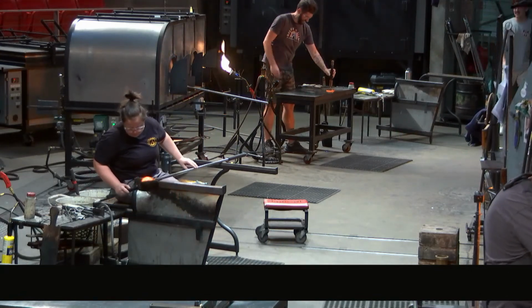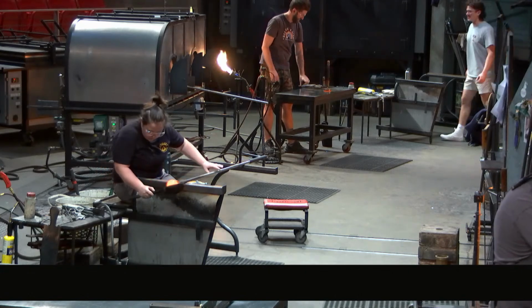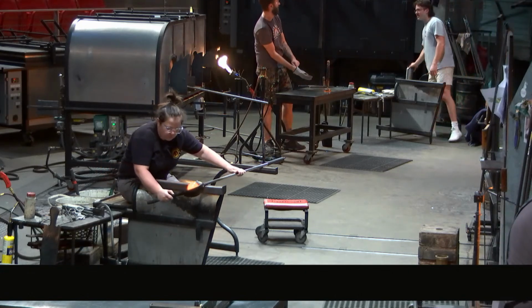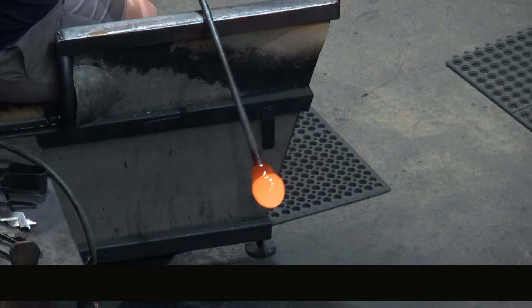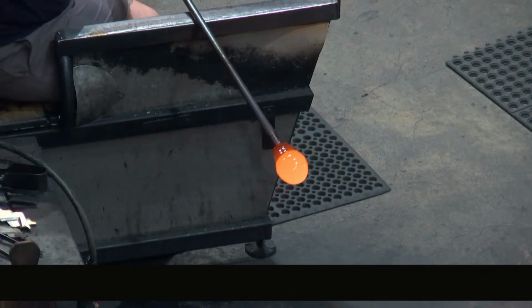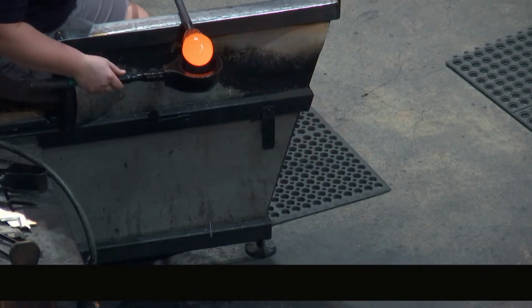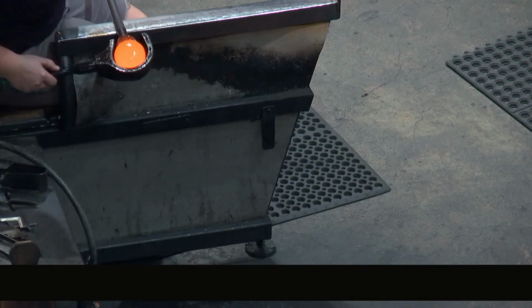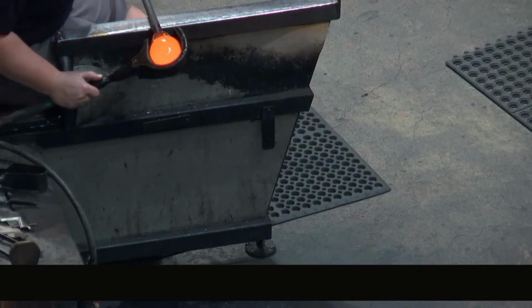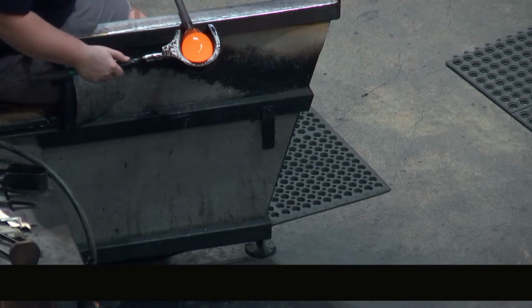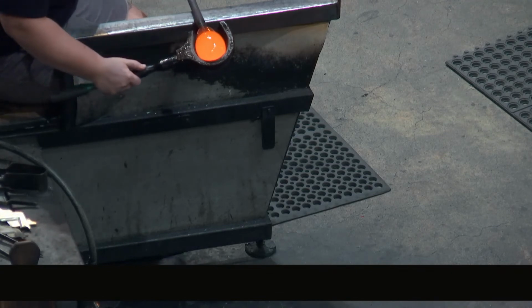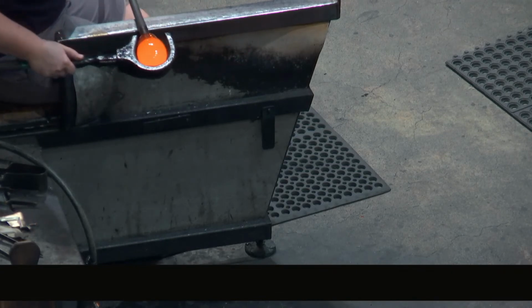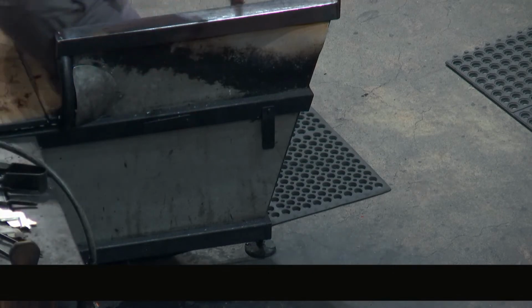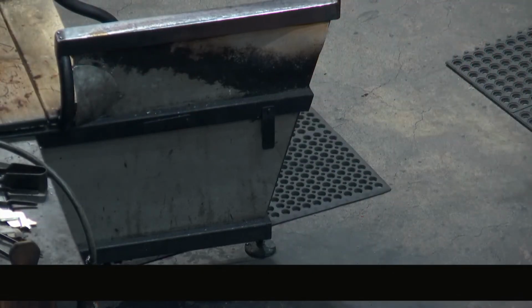Now, as you can imagine, with all of those inward-facing spikes, how do we pull the glass out if the spikes are going to be pushing inside the glass, kind of grabbing onto it? So it's a really difficult process of making sure you're not pushing it in too far or leaving it in there for too long. We have to kind of wiggle it out and go very quickly so that nothing gets stuck inside of that mold. And I have seen glass get stuck inside of these molds a couple of times. It just happens sometimes.